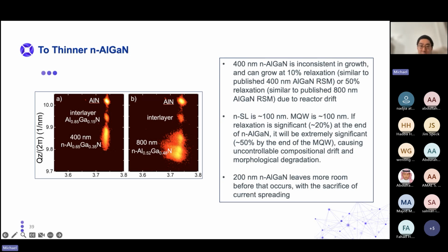So what we did was we thinned down our n-AlGaN to 200 nanometers. And that is basically just avoiding the problem and giving us more room to grow our quantum wells. Definitely this is sacrificing our current spreading, but because of Dr. Abdullah Al-Megbul's great work on the highly conductive n-type AlGaN, we still have a bit of room to work with in terms of conductivity of the n-type material.